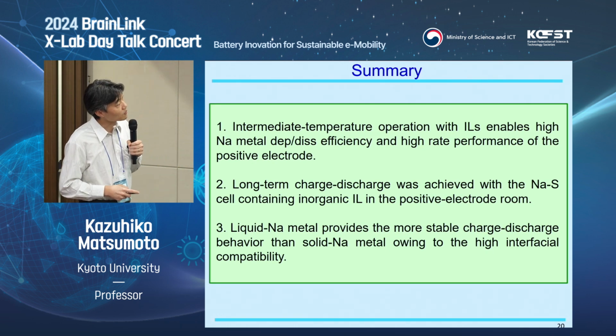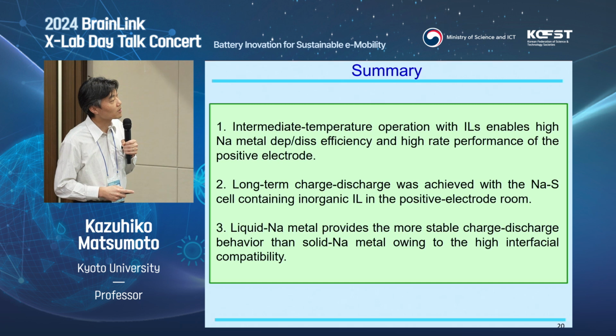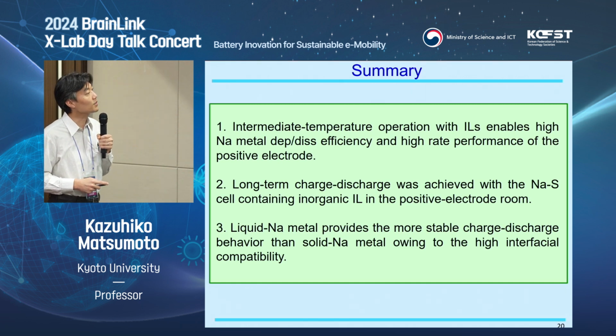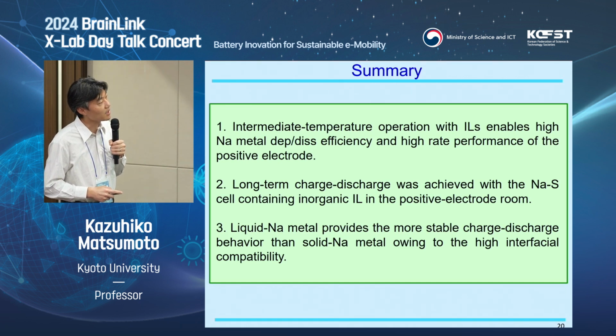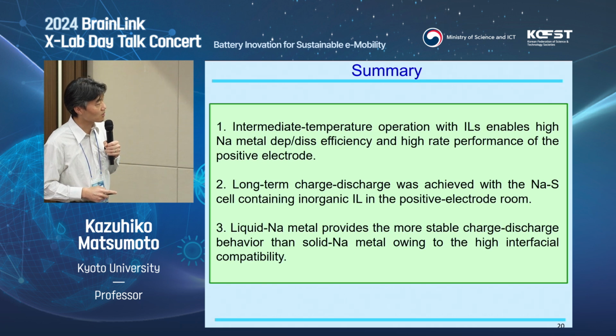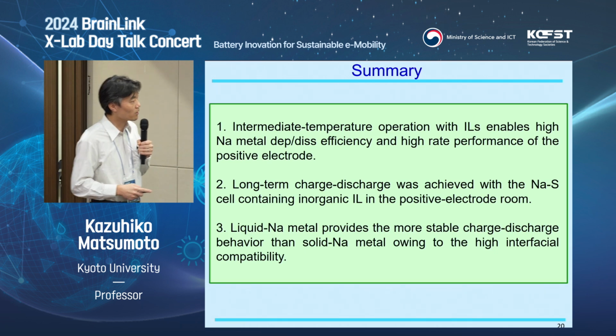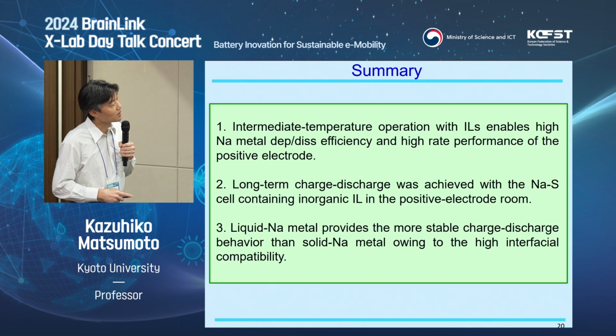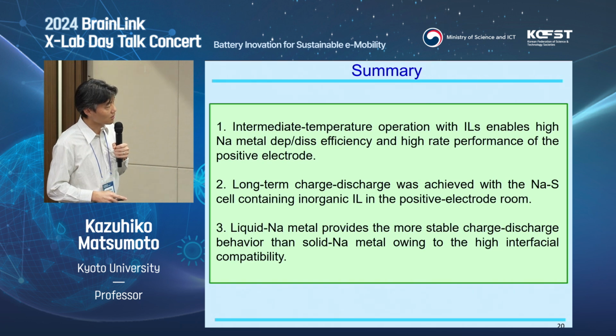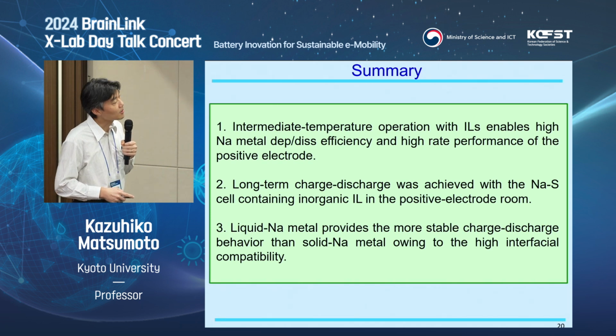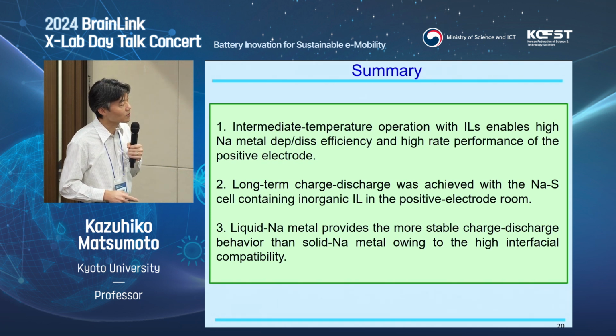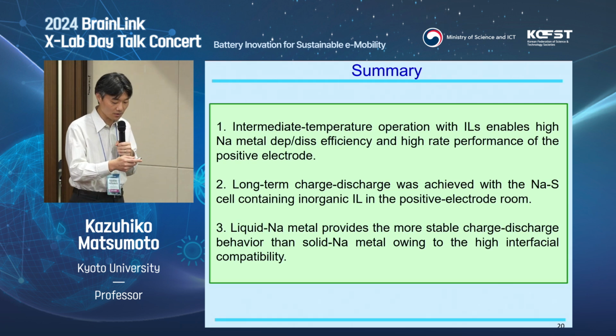And first, the intermediate temperature operation with ionic liquids enables high sodium metal deposition, dissolution efficiency, and also high rate performance of the positive electrode. In the second, long-term charge discharge was achieved with the sodium sulfur cell containing inorganic ionic liquid in the positive electrode room. And then the third one is liquid sodium metal provides a more stable charge discharge behavior than the solid sodium metal, owing to the high interfacial compatibility.